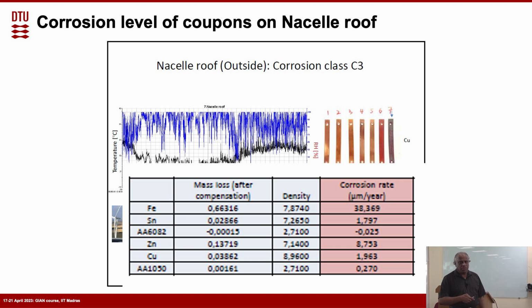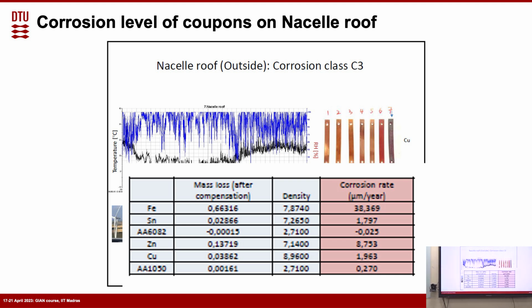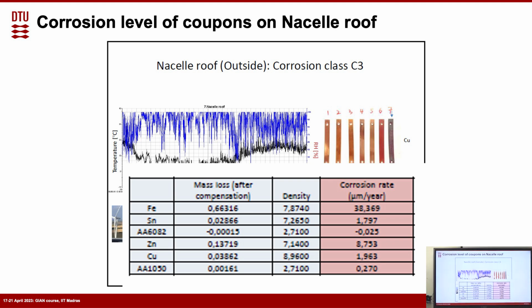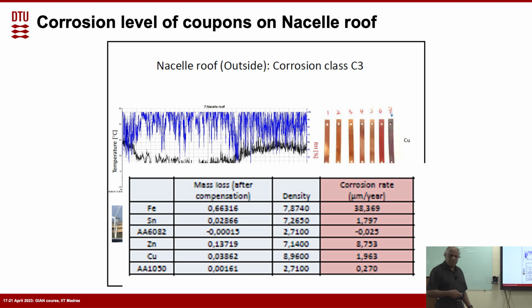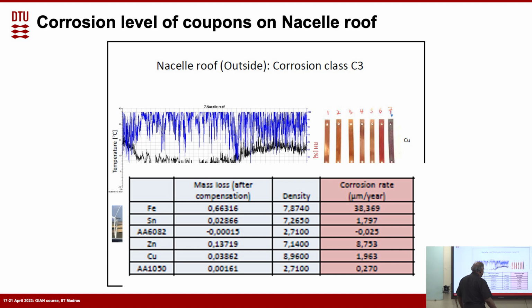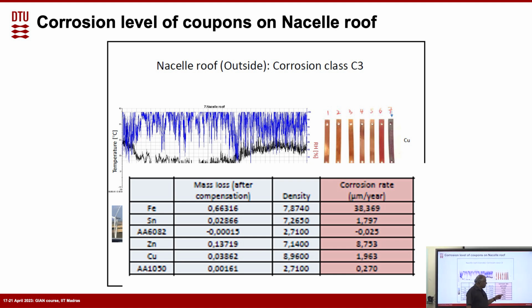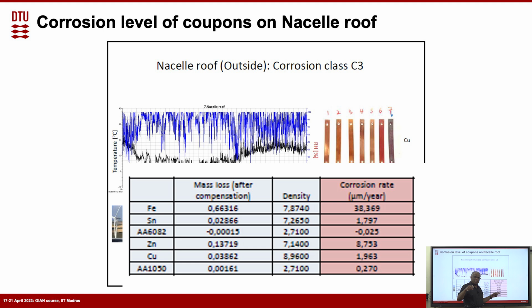Yeah. So it's not just based on one metal, but it's considering the whole different things like the distribution of copper, zinc and iron. Yes, exactly. Similarly for zinc as well. And so you can see that if you take this value of the iron and this value of the zinc, in both cases it is close to C3.